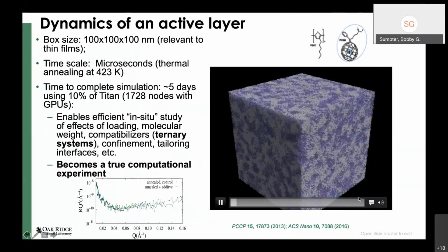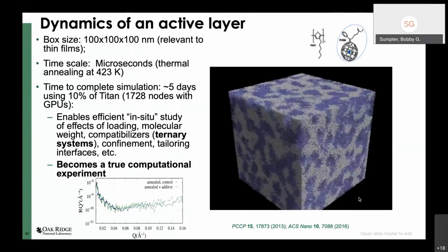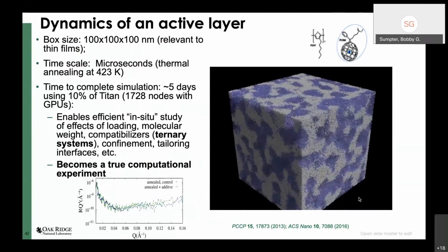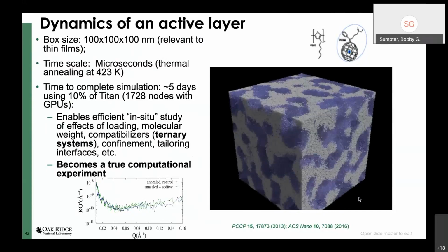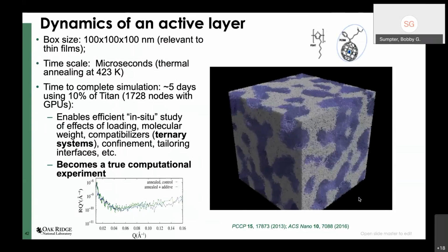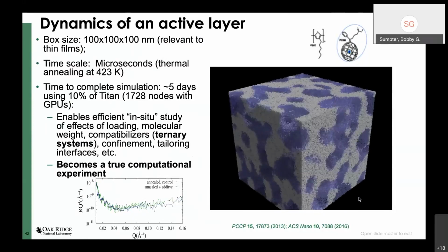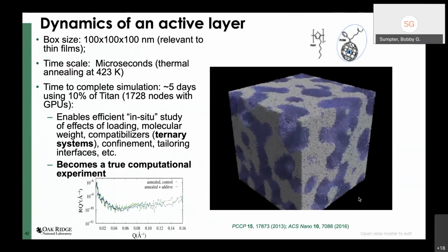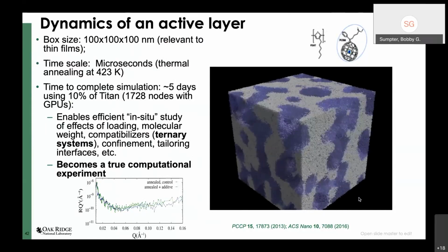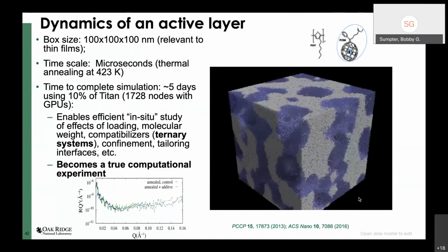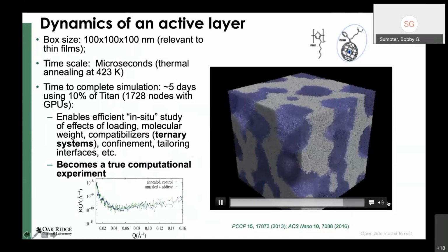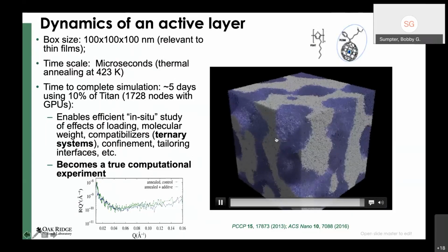Initially, it was randomly distributed, and over time, you start to see this nucleation and aggregation of the white molecules, which are the polymers, into domains, and the acceptor molecules, which are the C60 molecules, into other domains. The idea is if you can control that separation to within 10 to 20 nanometers, you can get the most efficient generation of electrons from photons in this photovoltaic system. And you can see over time it starts generating these domains that are around 10 to 15 nanometers in length.